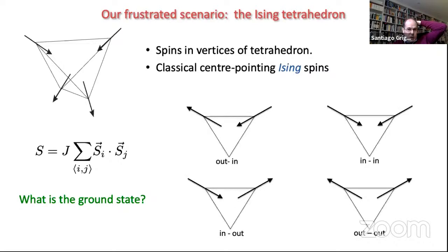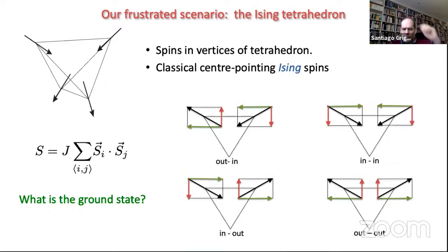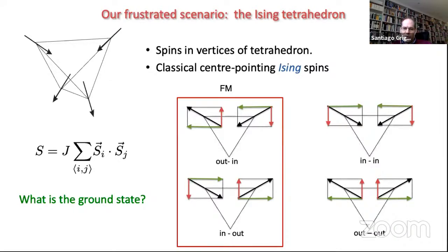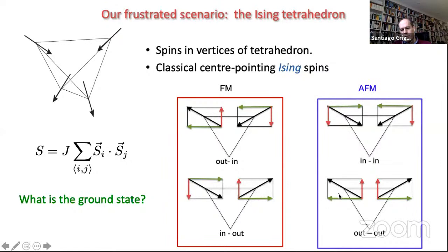Okay, so we explore the configurations. There are not that many, because it's pairwise interactions. We take a pair of spins, and you see that I can either put this pair of spins one pointing in, one pointing out, or both pointing in and both pointing out. So now, if I look at the components of this magnetic moment, you see that when I have a configuration which is either out-in or in-out, that tends to favor a ferromagnet. You see that here the long moments are the green ones, and they're oriented ferromagnetically. So if I add a ferromagnetic interaction, they would favor these configurations, while both pointing in or both pointing out are predominantly antiferromagnetic. So an antiferromagnetic interaction would favor this as a ground state.